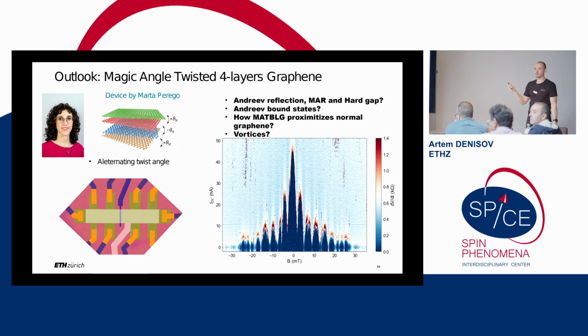Why do you have 4 layers, not 2? If you use 2, in order to get superconductivity you really need to hit an angle. It really should be 1.08 to 1.12. It's a bit more chill with 4. You can actually have an offset of 0.4, so it's not so demanding in terms of fabrication and your yield is better. It's a bit longer to stack 4 compared to 2, but almost all devices are actually superconducting.